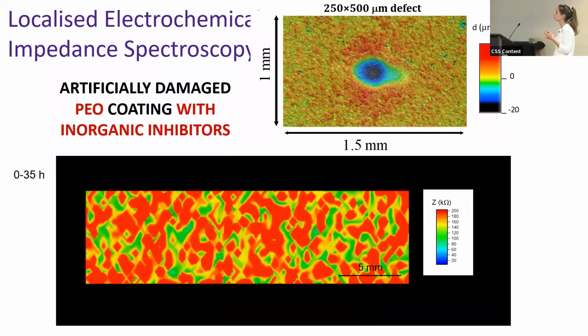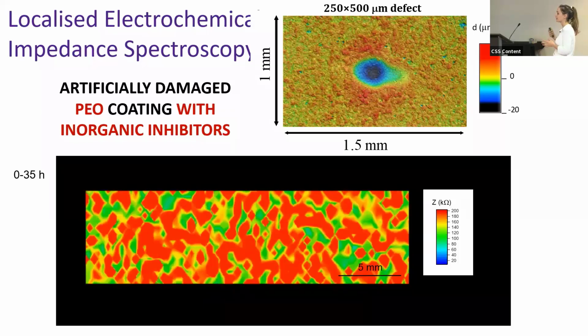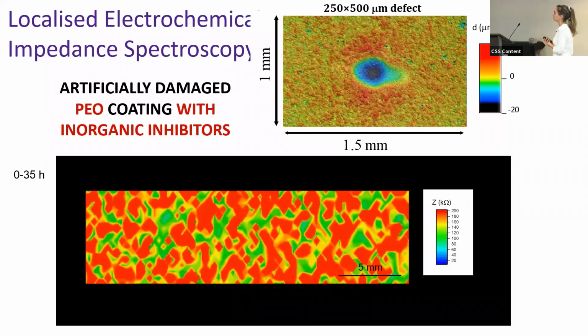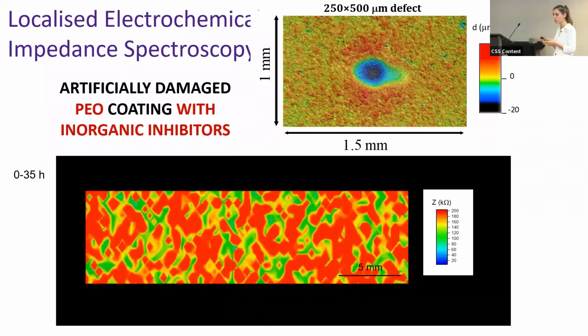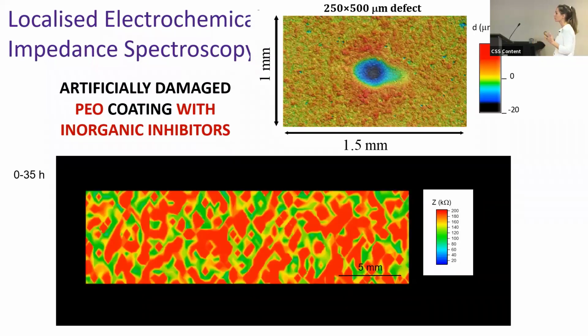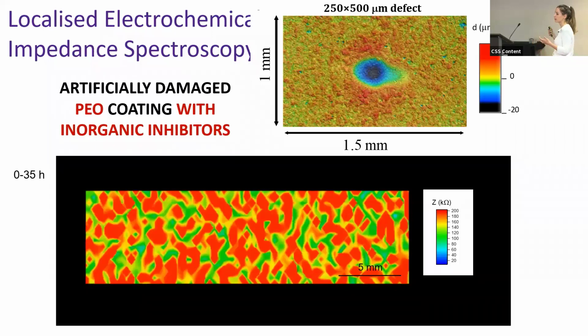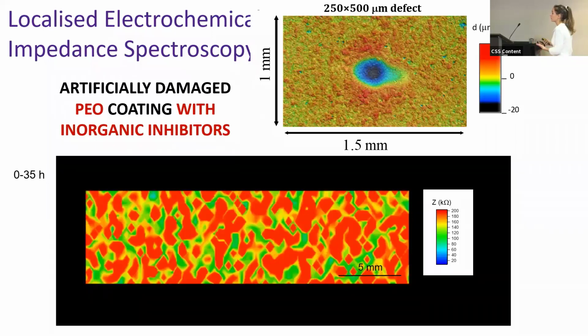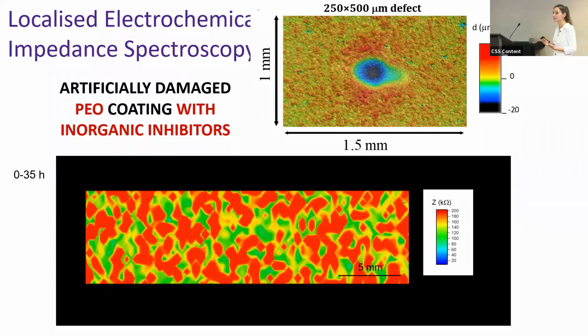It's worth mentioning that we only observed this self-healing effect on the inorganic inhibitors, which evidences the importance of the encapsulation to obtain a controlled release of these active species.